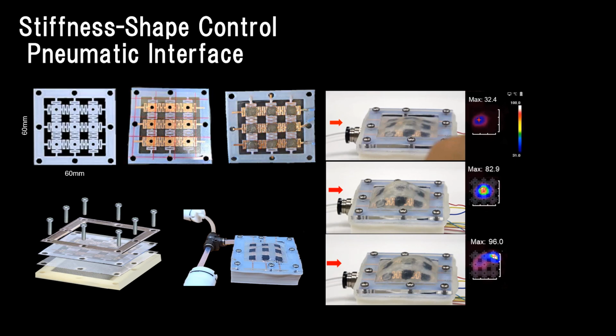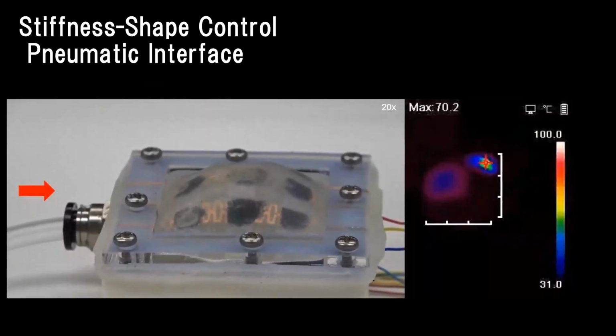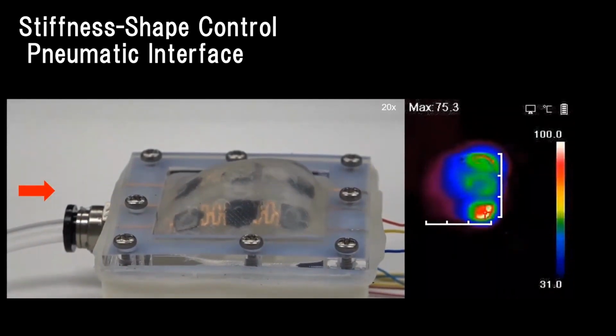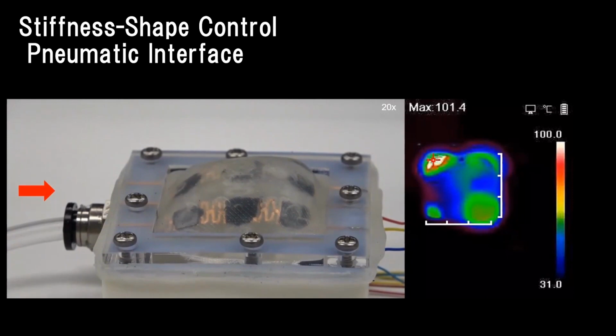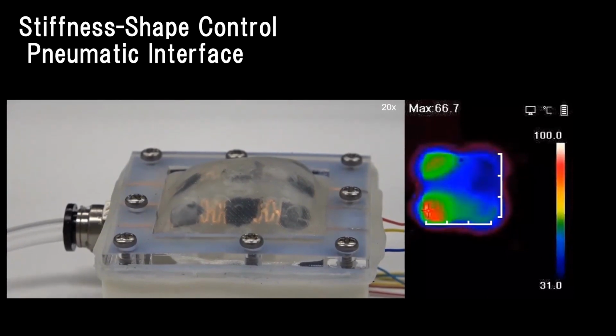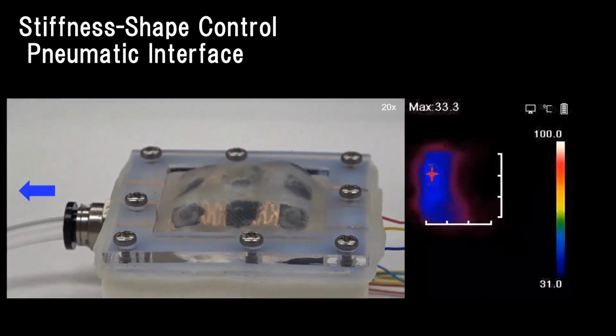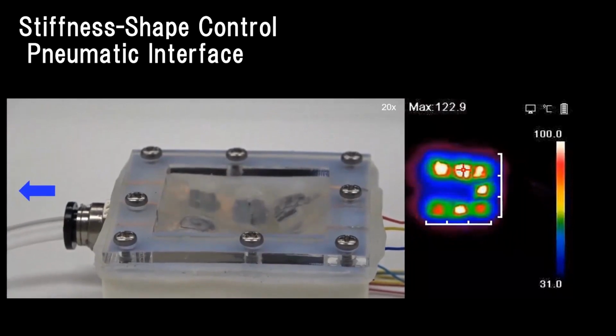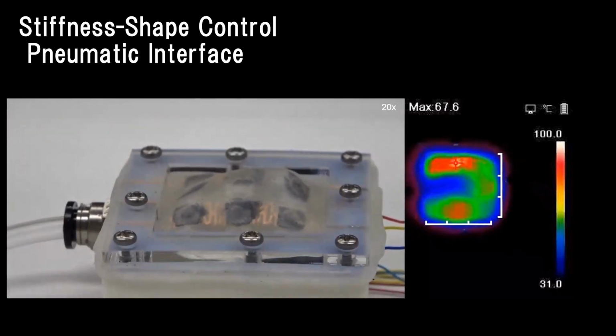We fabricated an expandable 3x3 mesh exoskeleton with built-in grid array heater and control the local inflation of the silicone membrane by tuning the node stiffness with the temperature. As expected, the silicone membrane inflated differently based on the heating pattern, demonstrating multi-mode pneumatic shape change at constant pressure. The shape was fixed and reset based on the thermal state of the mesh exoskeleton.